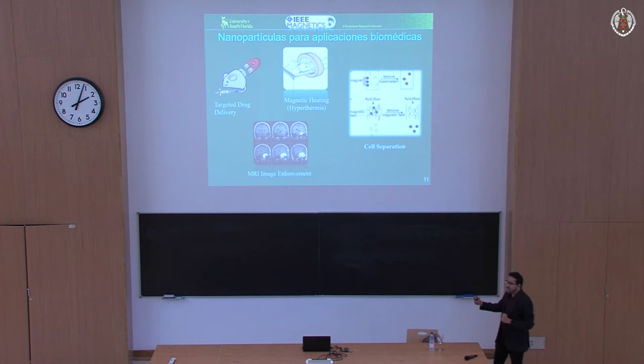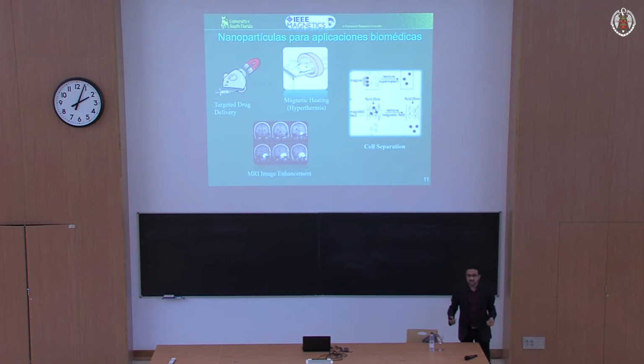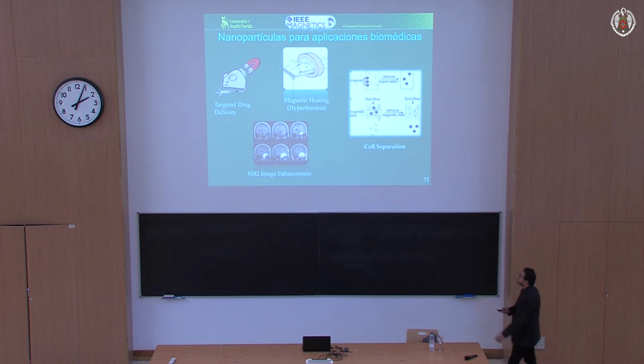Now what happens if we take magnetic nanoparticles and introduce them locally to the area? Due to the fringing fields of these nanoparticles, the fringing fields interfere with the relaxation time. In fact, it slows down the T1 and T2. And from this difference, you can get an enhanced contrast of the MRI images. This has been validated. It's a very well-established technique now that magnetic nanoparticles can indeed improve the MRI images, okay? So that's a very important breakthrough in nanomedicine.